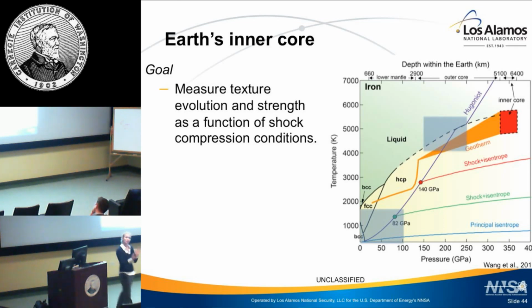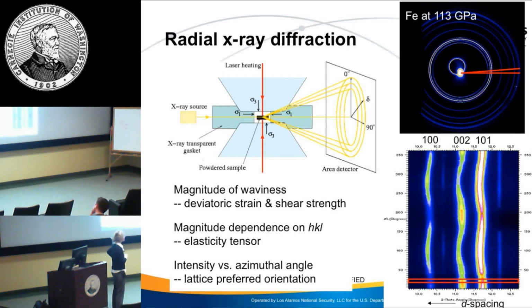Lower pressure, where we can actually overlap with static compression strength data, and then we're going to push it as high as we can and go all the way up to try to achieve melt and just crisscross above and below that melt bound. So from a static compression perspective, radial X-ray diffraction affords us the opportunity to observe the maximum deviatoric strain by non-hydrostatically compressing our sample, and then probing perpendicular to the compression direction.